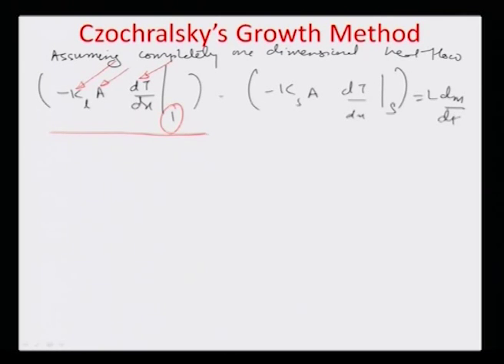And of course, this heat goes into the zone, and the heat which is lost from the zone of fusion into the solid can be defined as minus Ks A dT by dx, where Ks is basically the thermal conductivity of the solid material, times the interfacial area between the zone of fusion and the solid, A. We assume the area to be the same in both the cases for simplicity of the model, times dT by dx, the temperature gradient in the solid while the heat flows from the zone of fusion into the solid. Okay, so that is the difference of heat flow into the zone of fusion and outside the zone of fusion, and this net heat loss here is recorded as the solid formation, the heat of formation of the particular solid.